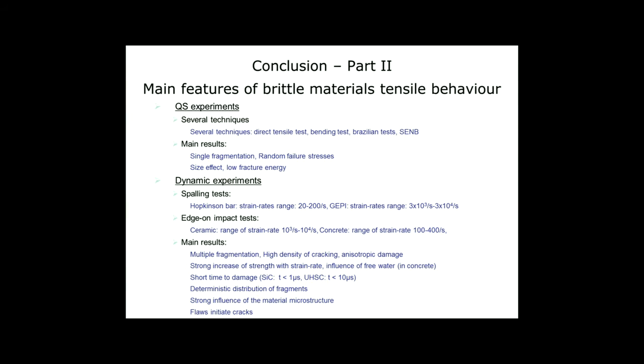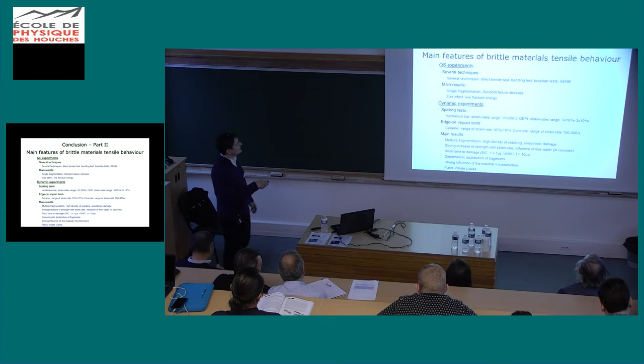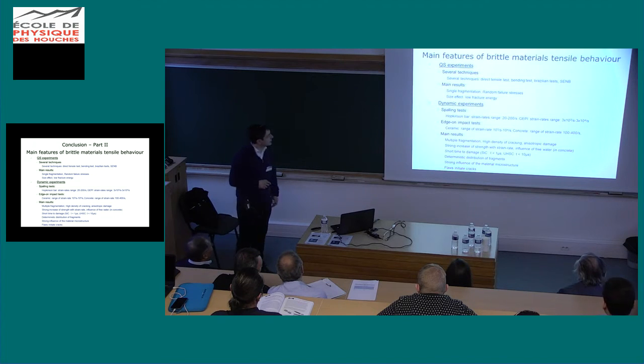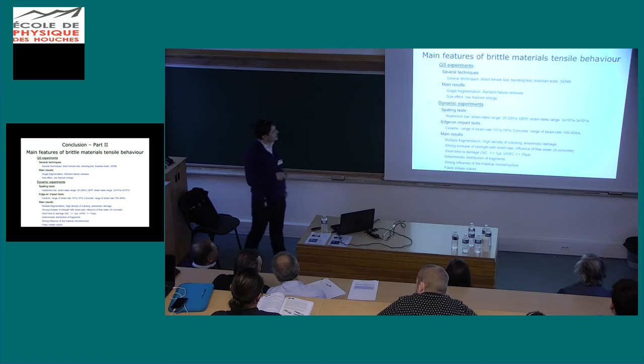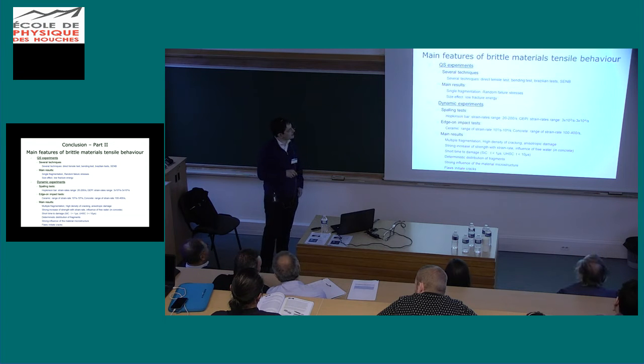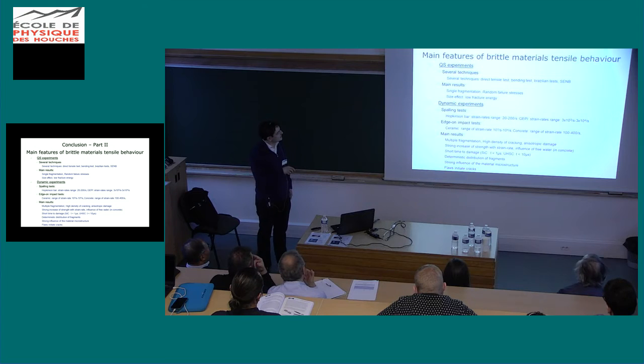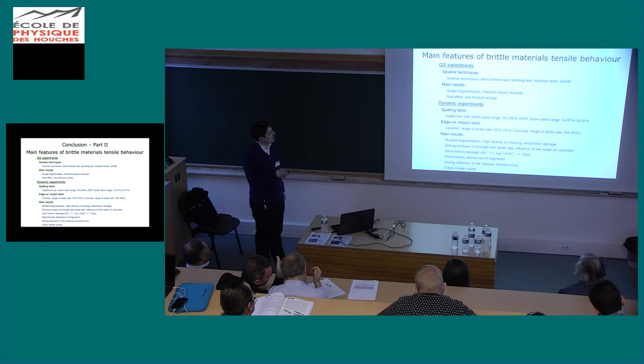So to conclude this part, you can see several techniques can be used for quasi-static experiments, like direct tensile test, bending, Brazilian test, etc. The main result is that failure stresses are random. Single fragmentation occurs in quasi-static, a size effect is observed, and we can also observe with brittle material that the fracture energy is low.